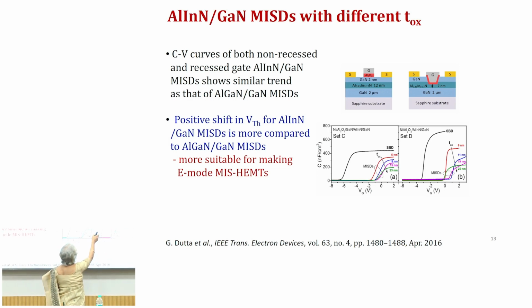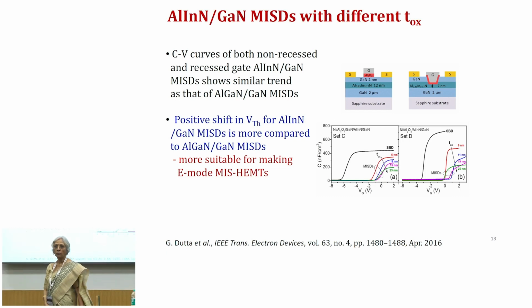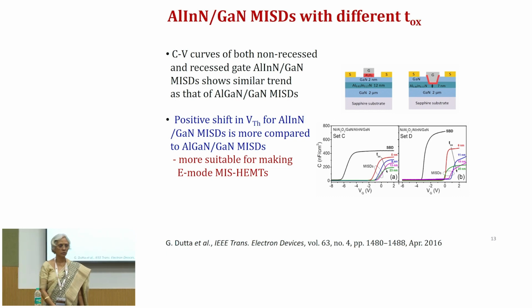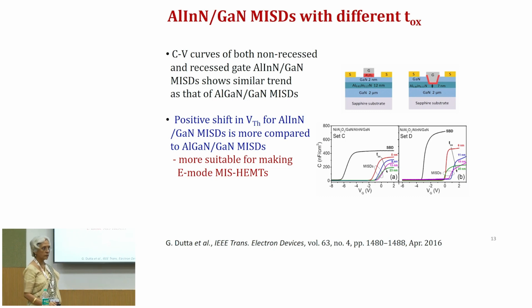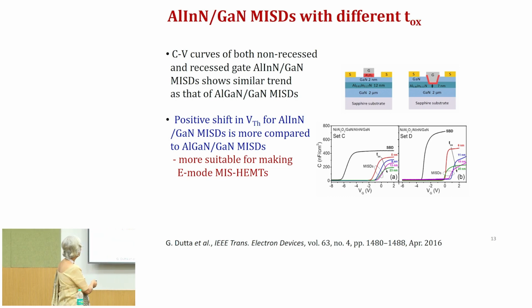Similarly, you can see here, this is the set D, that is the recessed gate oxide, and here also you can see from 6 nanometer to 11 nanometer to 19 nanometer it is increasing, but then when you go to 25 nanometer it actually goes back, the threshold voltage starts to go back to more negative direction. So, what do we see? We see that as we increase the gate oxide thickness, the threshold voltage becomes more and more positive, but beyond a certain point it starts to reduce again.